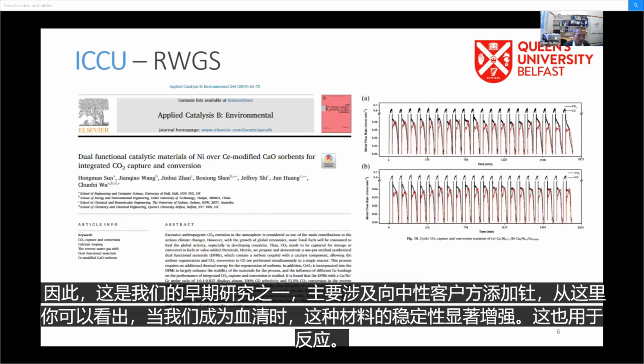This is one of our early works, mainly about the addition of cerium into the nickel calcium oxide. From here you can see that when we add cerium, the stability of the material is significantly enhanced. This is also for the reverse water gas reaction.